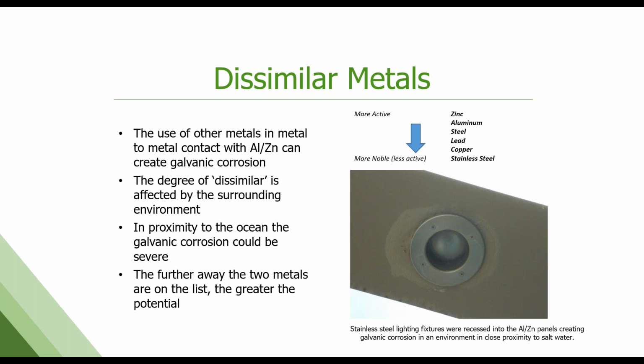What I have here is an example of a Galvalume painted panel with a stainless steel lighting canister recessed through it with no barrier between them. And all of that staining and corrosion you see around the lighting canister is the Galvalume panel sacrificing itself to protect the stainless steel. Now, if this wasn't near the ocean, it wouldn't be a problem, but because it's in a saltwater environment, it's a huge issue. This site was about 300 feet off the surf break in Southern California, so high salt content. Next slide.